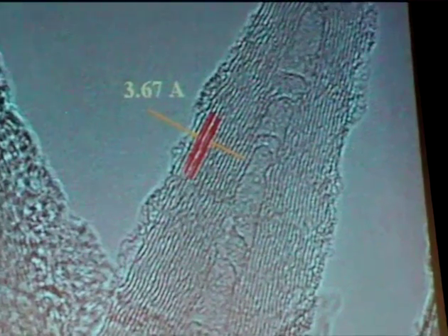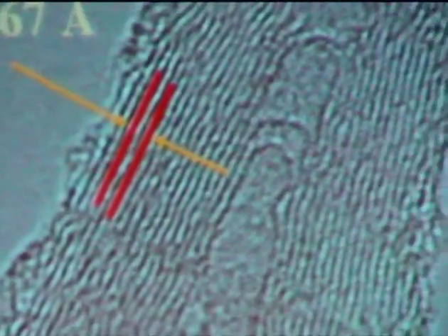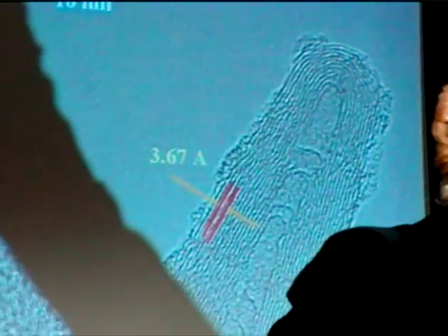The little round area that I had highlighted shows, under much larger magnification, what's really going on there. We're not only having wires, we have tubes. Actually, something that at first reminded me of a carbon nanotube, but this is an oxide nanotube of gallium oxide, and you have the d-spacing, 3.67 angstroms, corresponding to the 201 planes of beta gallium oxide, Ga2O3. This is just another example where again you have a tube. This is semi-hollow in the interior, and again the d-spacing is 3.67 angstroms across.